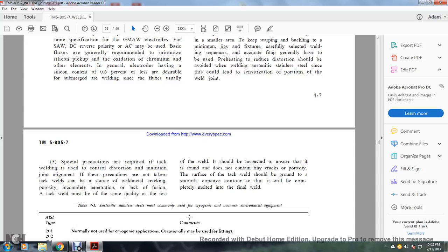Alright, special precautions are required when tack welding, using controlled distortion to maintain the joint alignment. If these precautions are not taken, the tack welds can be a source of weld metal cracks, porosity, incomplete penetration, and lack of fusion. The tack weld must be made to the same quality as the rest of the weld. It should be inspected to ensure that it is sound and does not contain any tiny cracks or porosity. The tack weld should be ground with smooth and concave contours so that it will be completely remelted with the final weld.